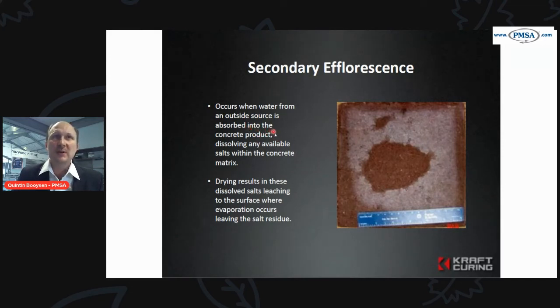So the water is absorbed into the concrete product, dissolves salts, and it forms within the matrix, and it pulls through to the surface. The drying results in these dissolved salts leaching to the surface, where evaporation occurs, leaving the salt residue behind.